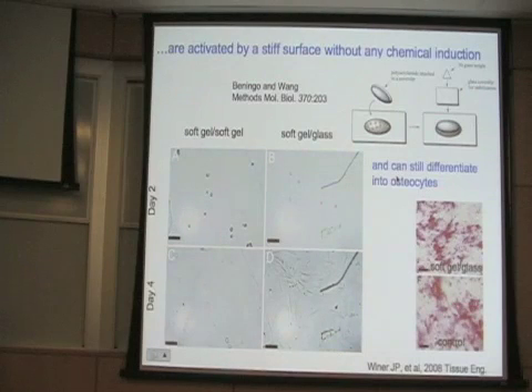And one of the reasons we can show that they are still happy is by making one of these little sandwiches. So the experiment is like this. We've grown the cells on a soft gel for several days, and they've become quiescent. So here are two different cell populations on soft materials.